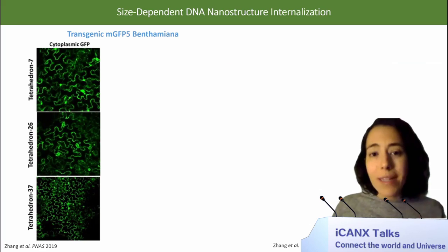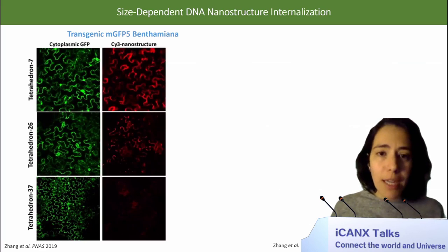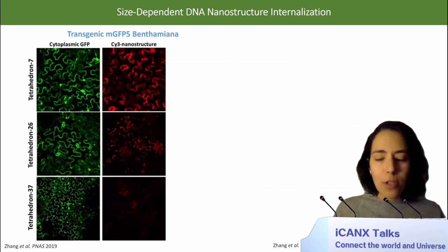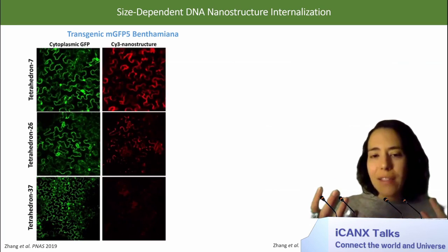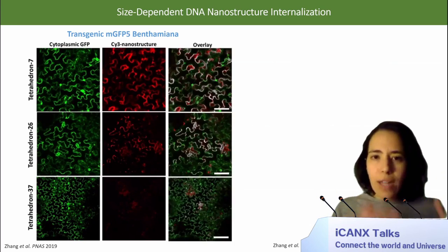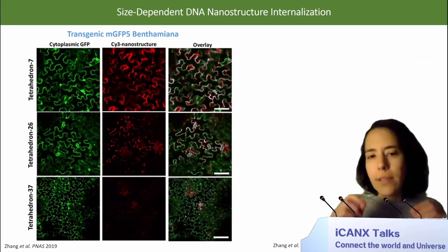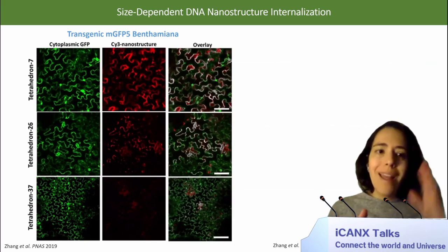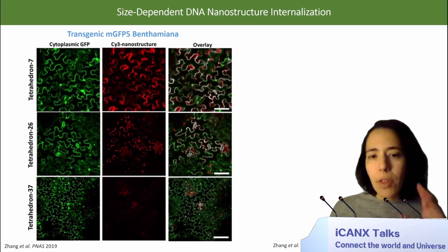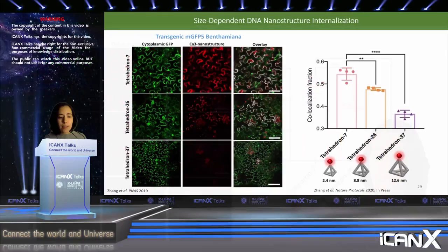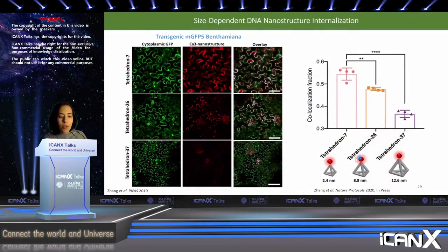We can then also fluorescently label our DNA nanostructures with Cy3 dye, inject those into the plant tissue, and then through a colocalization analysis, look at the relative levels of internalization as a function of some parameter by calculating the colocalization fraction between the Cy3 nanostructure channel and the cytoplasmic GFP channel. If we look at the effect of internalization on something like size, for example, as a function of size, 2.4, 8.8 versus 12.6, we see a much higher colocalization fraction for the smaller nanoparticle than the larger nanoparticle. These results are as we would expect. As particles get larger, it becomes more and more difficult for them to internalize into the plant cell cytosol.